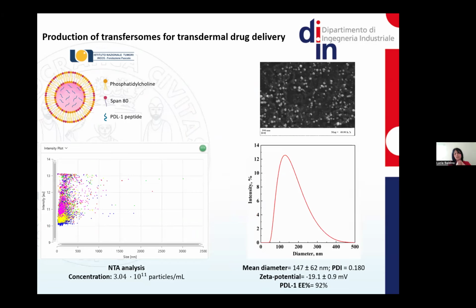In this last example, we produced transfersomes for anti-cancer treatment, and we loaded this kind of vesicles with a peptide synthesized ad hoc by our colleagues of the National Cancer Institute Pascale Foundation of Naples. As you can see, after processing, we obtained nanometric transfersomes with a unimodal size distribution, a mean diameter around 150 nanometers, a zeta potential value of minus 19 millivolt, suggesting stable vesicles. Moreover, we also reached a peptide encapsulation efficiency up to 92%.